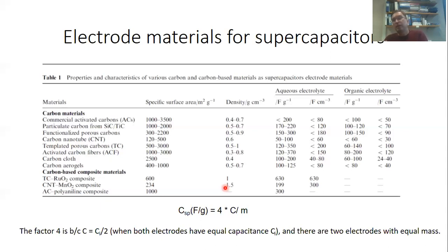But this only typically occurs at much higher voltages, in the order of hundreds to thousands of volts. Okay. Still, although you can apply higher voltages to a parallel plate capacitor, the capacitances are still much smaller just because of the higher internal surface area of supercapacitor electrodes and the sub-nanometer distance between the charges in the electrodes and the